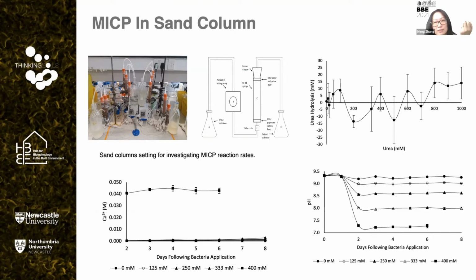This finding is in line with other literature, and when the calcium ion increased to a higher ratio, you can see the calcium ions were not fully precipitated and can also be detected in the effluent, as shown on the left-hand figure here. Another interesting observation is that when we increase the concentration of calcium chloride in the system, it leads to a decrease of pH in the sand column. Particularly when we add 400 millimolar into the system, it decreases to pH 7.2, which is really not a favorable condition for calcite precipitation.